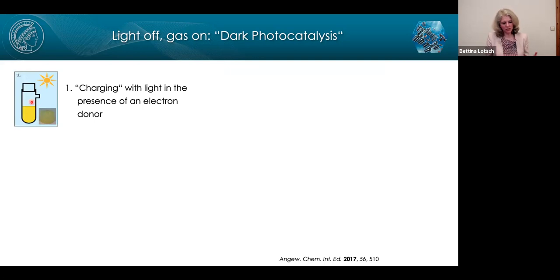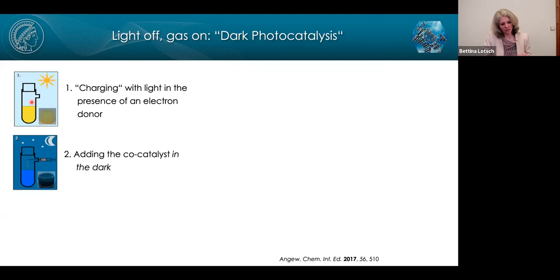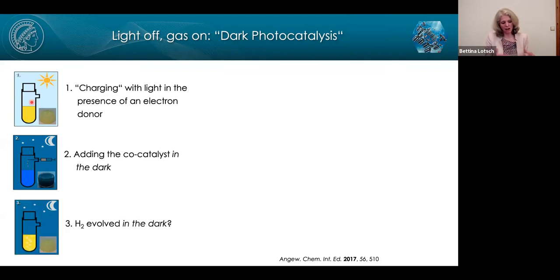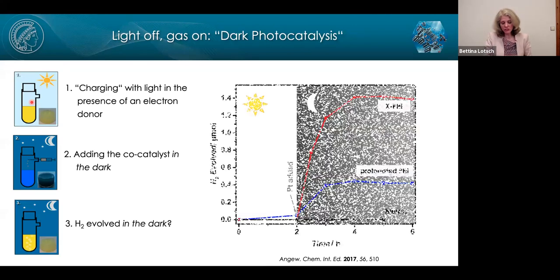So we asked ourselves, is it actually possible to photocharge the carbon nitride in the light in the presence of an electron donor, then turn off the light and add a co-catalyst in the dark? Because remember, without a co-catalyst, the system does not give off hydrogen, essentially, right? And then can we sort of harvest the hydrogen with a time delay in the dark? And so the answer is yes.